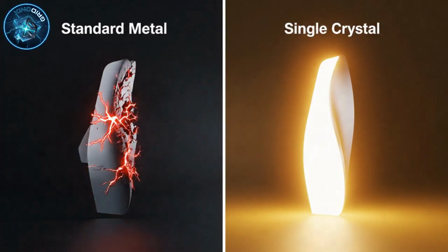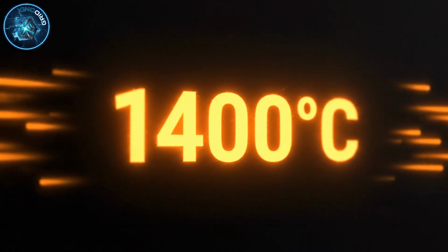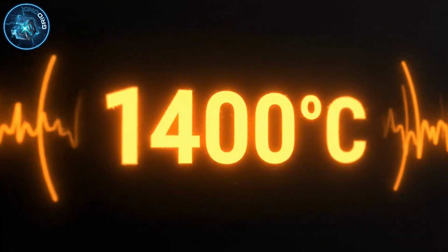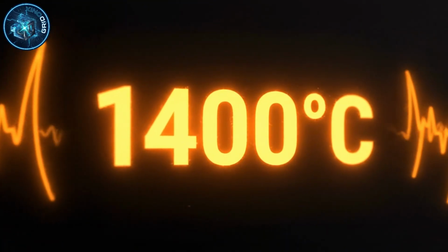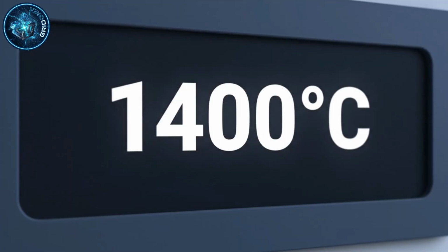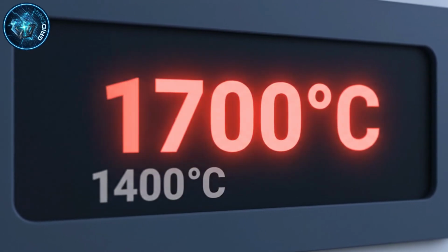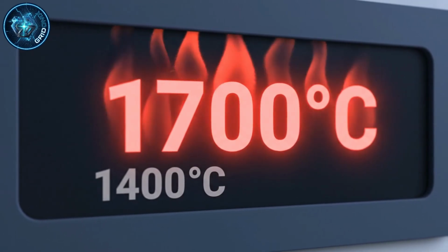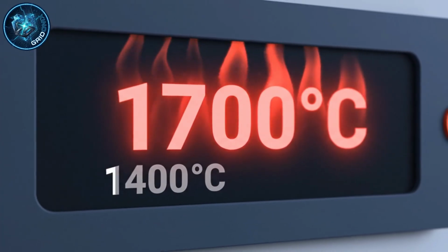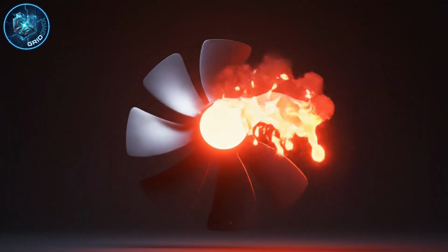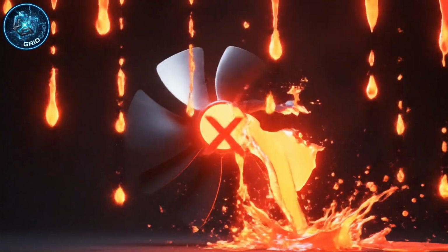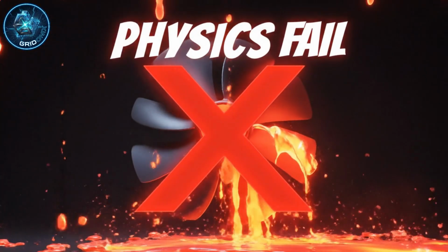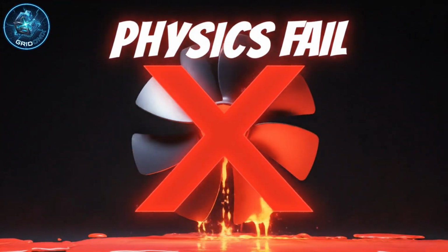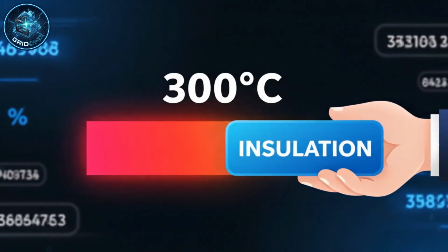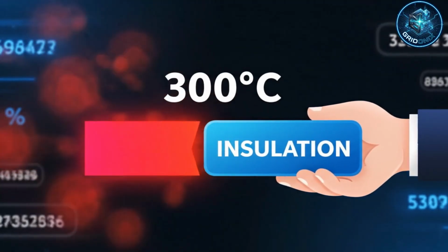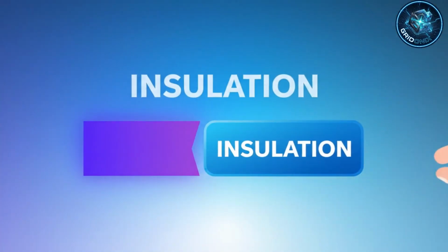However, we must return to the numbers. A single crystal superalloy melts at roughly 1,400 degrees Celsius. The gas coming out of the combustor is 1,700 degrees. The physics still says the blade should die. The metal is strong, but it is not invincible. To bridge this 300-degree gap, we have to cheat thermodynamics. We have to insulate the metal.